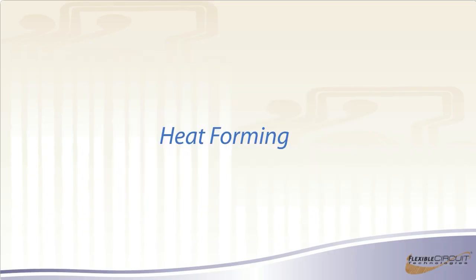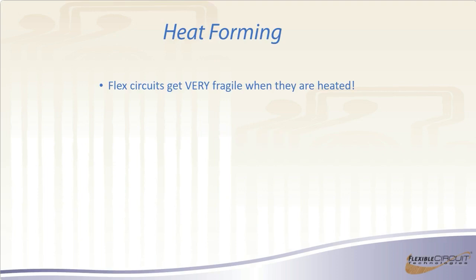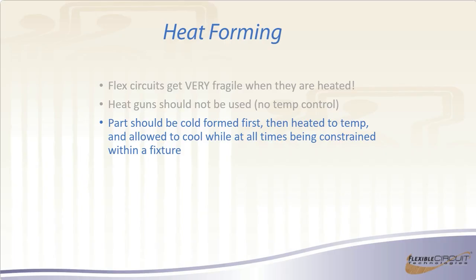Heat forming. Keep in mind, if you're going to heat form, circuits get very fragile when they get hot. Don't ever use a heat gun because it's not controllable. 1 inch away from the nozzle, it's 900 degrees. If you're a foot away, it's only 150 degrees. So it's not really something that's good to have on the floor. You always want to cold form your circuit first, then heat it to temp in a fixture. Allow it to cool at room temperature, still constrained within that forming tool, and then remove it from the tool.